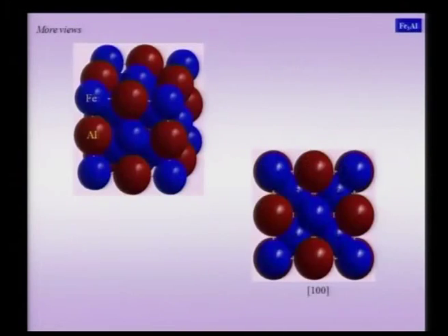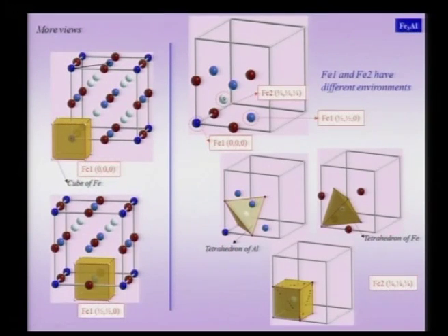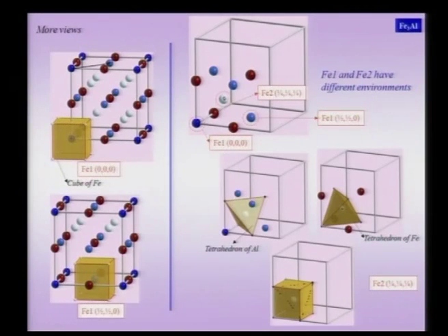So clearly they are non-equivalent positions with regard to the coordination polyhedron, and the number of such equivalent atoms within the unit cell is also different. There are 8 belonging to this type and there are 4 belonging to this type, and this calculation is easy to make because we know there is 1 contribution from the corner atoms and 3 from the face centering atoms. So there are 4 of this type and there are 8 of this type.